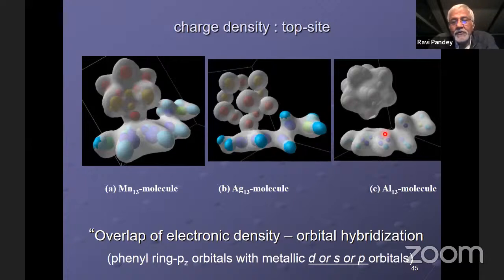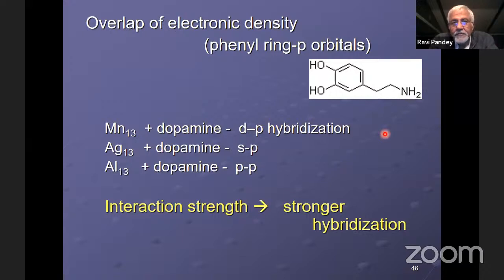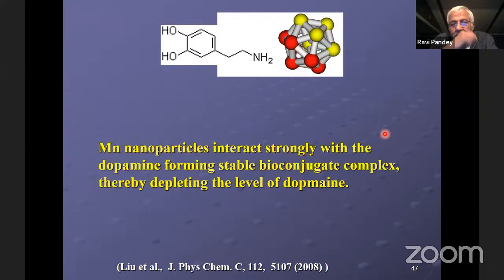So it comes down to the effectiveness of the nanoparticle interacting with a biomolecule, and what kind of bonding they're going to form at the interface. So pd hybridization is going to be preferred over sp or pp. And definitely it tells us that once these manganese nanoparticles interact strongly with the dopamine, they form a very, very stable complex. And if the complex is formed, then definitely we are not going to see the individual dopamine level in the system.